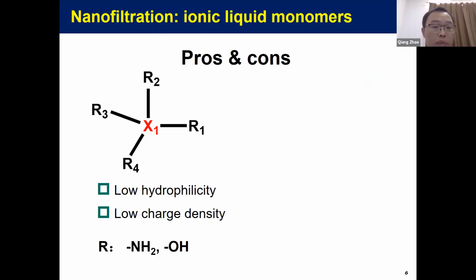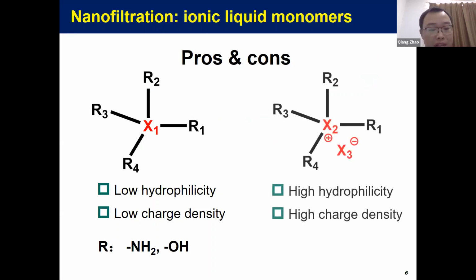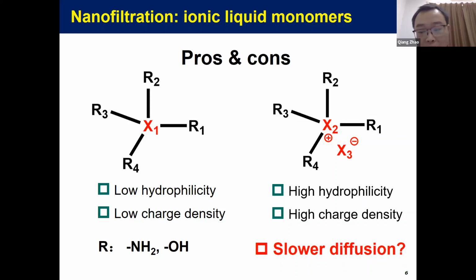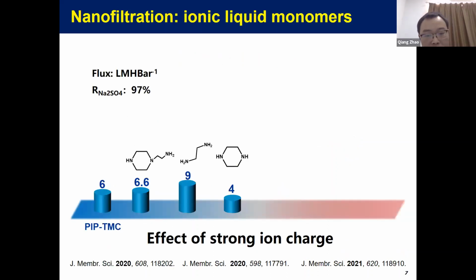For a conventional monomer, we have a pros and cons analysis. They feature less hydrophilicity, but if you introduce strong charge into the monomer, you improve the hydrophilicity and you improve the charge density. But the side effect is that the charged monomers usually feature slower diffusion in the organic phase, which could be problematic in interfacial polymerization. And our motivation to compensate for this side effect is to introduce more reactive amine groups. So here is the summarization.